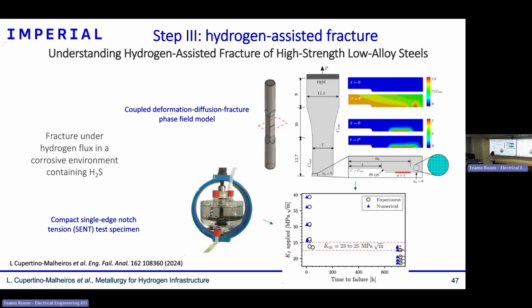So the way you can interpret this here is the time to failure. So those samples that are at times before here, 200 hours, have failed. The ones over there, they didn't fail. And this K1 is related to the force that has been applied. And very important here, we can determine the threshold value, so the value necessary to fracture those samples. So above it all those samples fracture, below it no samples fracture. And we got a very good correlation between our experiments and the numerical modeling. So this is actually the final result that I want to show to you today.